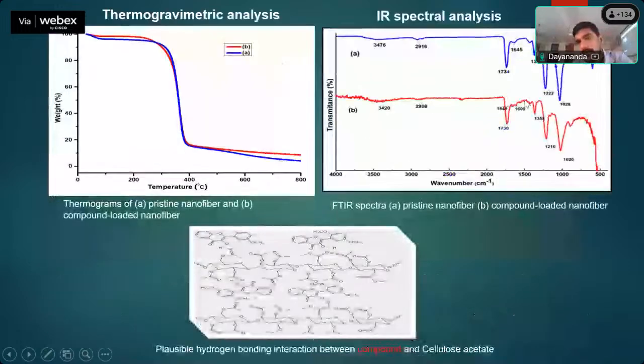To know the functional group present in the polymer as well as in the drug load, since the loading was very less—only 5% loaded in the nanofiber mat—the peaks corresponding to the compound could not be clearly seen. Only one peak could be observed at 1649, which could be due to the CO functional group.